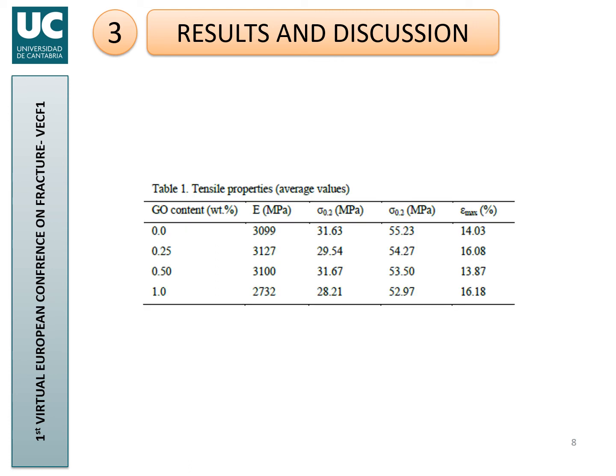Here you have a summary of the results. You see that the yield stress has a tendency to be reduced when including nanoparticles. The Young modulus actually is not very sensitive, except for the case of 1 weight percentage. The ultimate tensile strength, there is a typo there, which is the second column from the right, is rather constant as well, but it tends to be lowered when including nanoparticles, and the ductility has certain increase when including the nanoparticle.